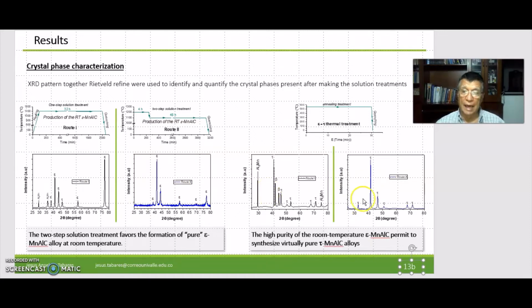For the epsilon phase-based alloy obtained by following route 2, the pure epsilon manganese aluminum carbon is totally transformed in the tau manganese aluminum carbon phase, without the presence of secondary phases. Thus, the high purity of the epsilon manganese aluminum carbon permits to synthesize a pure tau manganese aluminum alloy.